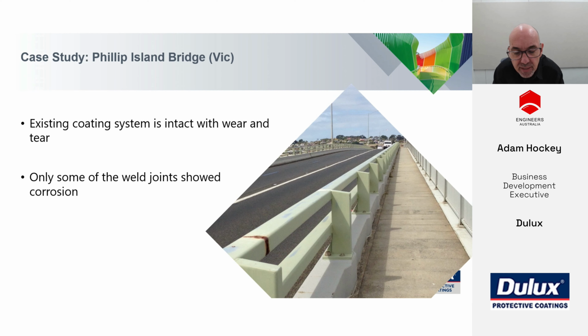If we take a closer look at the handrail, we can see that it's intact. There's no corrosion present. It's suffering some wear and tear, most likely from the UV radiation, which is quite high in Australia. If I use my special effect here, I can point out one area where I may have been misleading there and said there's no corrosion. There is one band of corrosion on that handrail or that guardrail.